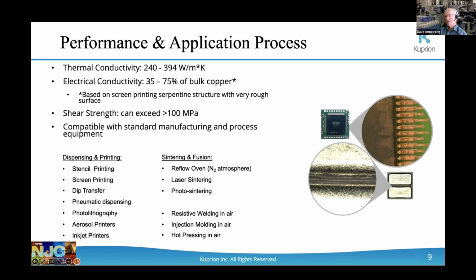Yeah, it does very much. It generates the other question, though, is how do you get the CTE the same as silicon? That feels like difficult. Yes, it is difficult. We actually do have a few different formulations. We have several proprietary fillers that we add to it that are low CTE and help adjust that. And depending on what you want to do, you choose the most appropriate one in terms of size, mostly. That you can either fill a small via in glass or a large via in a printed circuit board, or make a DBC aluminum nitride or things like that. Thank you.